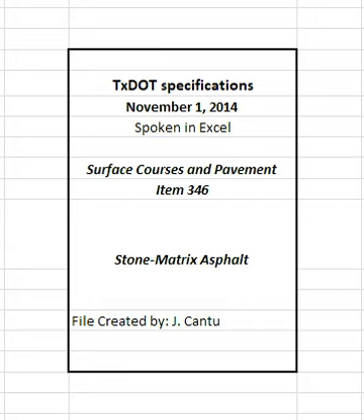The aging ratio is the DSR value of the extracted binder divided by the DSR value of the original unaged binder. Obtain DSR values in accordance with TxDOT T315 at the specified high temperature PG of the asphalt. The engineer may require removal and replacement of the defective material at the contractor's expense. The asphalt binder will be recovered for testing from production samples or cores in accordance with Tex-211-F.